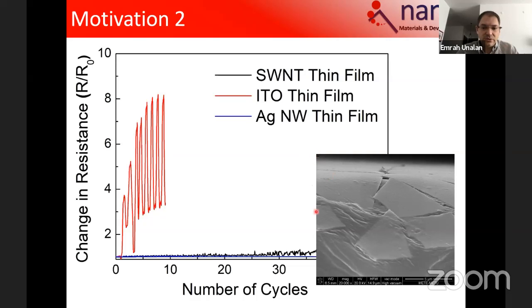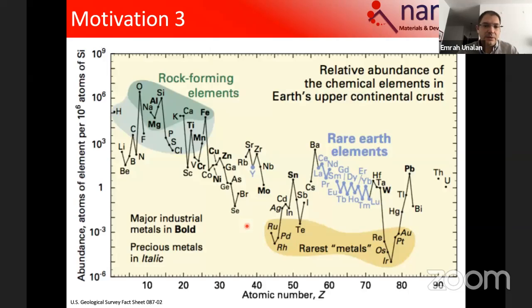And in this SEM image, on the bottom right, as you see, ITO cannot survive if you do a bending test. And if you also at the same time measure the resistance, as you see over here, the resistance diverges, or rises orders and orders of magnitude after a few bending cycles. But in contrast, as you see over here with the blue and the black, there are some alternative materials. One of them is the carbon nanotubes. Graphene would be the same, I believe, and also the blue one in here is going to be the silver nanowire thin film, which I will be talking about. So as you see, different material, and strain is no concern. Its flexibility is no concern, and it survives many cycles without breaking.